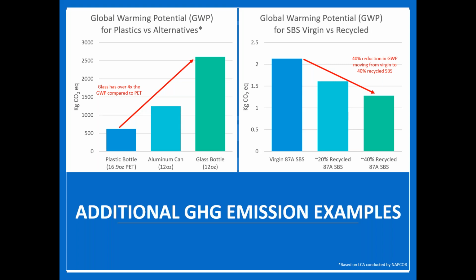And then another one is going to be virgin versus recycled SBS, a styrenic based TPE, where you're looking at the same hardness. You go from virgin and then you move down to 20% recycled content, 40% recycled content, up to a 40% reduction in GWP. So again, this is why we're talking about these sustainable plastics and their effect on global warming and greenhouse gases. This just gives you an idea of what that looks like and why you might look to use something that's recycled or sustainable.